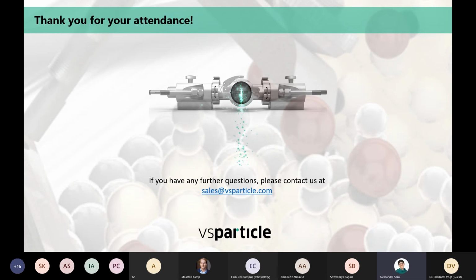Did you explore catalyst on other supports? Can you speculate on whether the structure insensitivity is translatable to other supports, for example, titanium? We explored structure sensitivity on different supports. We have nickel on all kinds of different supports of different reducibility, which showed us that the activation energy of CO2 hydrogenation doesn't actually change for the different supports, but the activity really does. Which means that the most contributing factor is whatever is caught in the prefactor of the Arrhenius equation, being the geometry of the active sites, most likely.